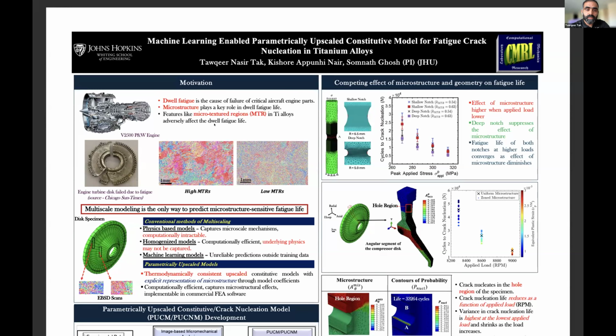The motivation for this research comes from the fact that dwell fatigue is the cause of failure of critical aircraft engine components like these disks. And microstructure plays a key role in the dwell fatigue life of these components. Here we can see microtextured regions in these EBSD scans that impact the fatigue crack nucleation, or in general fatigue life, of these components. This brings us to the key question.